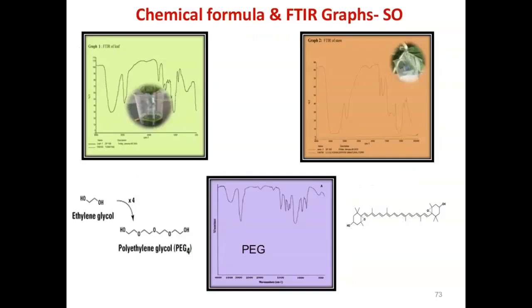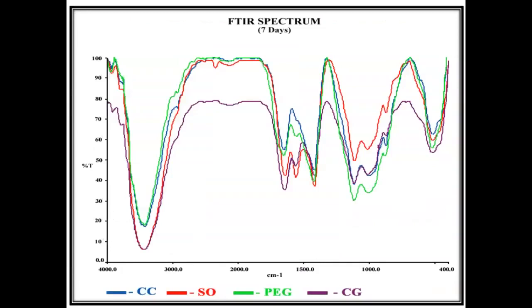And this is the FTIR study, Fourier transform infrared. This study gives the picture of how the structures and peaks are similar to that of polyethylene glycol. You can see the bottom picture shows polyethylene glycol, and the top two are collard green and Calotropis gigantea. The structures and peaks are similar to polyethylene glycol, so it has the property of holding water, which we have proved. Another one: after mixing collard green or Erukku in concrete, after 7 days we made the concrete into powder and did the FTIR analysis. Here also the graph, curves, peaks and stretches are similar to those of polyethylene glycol.